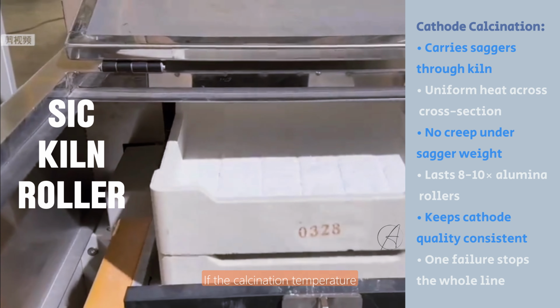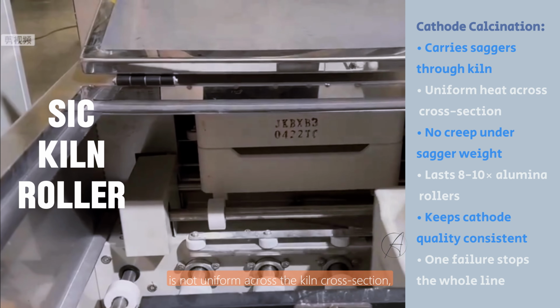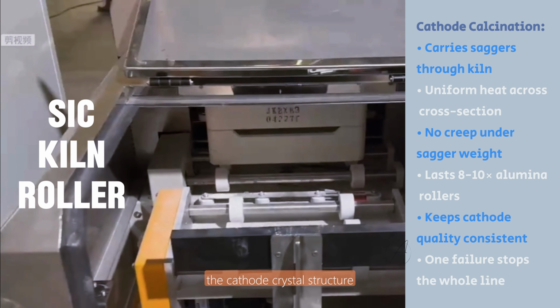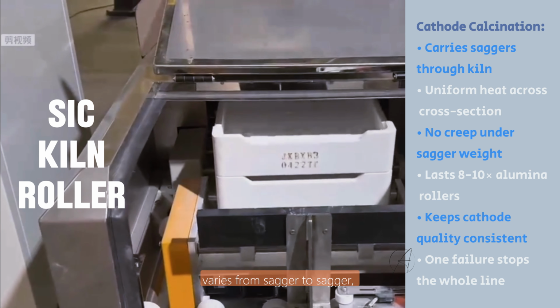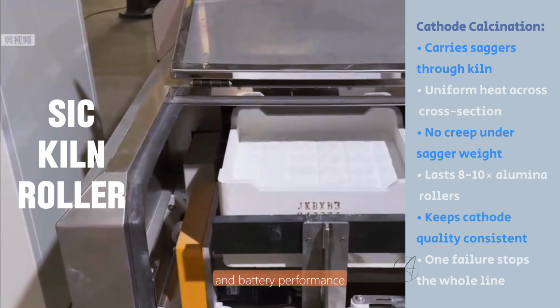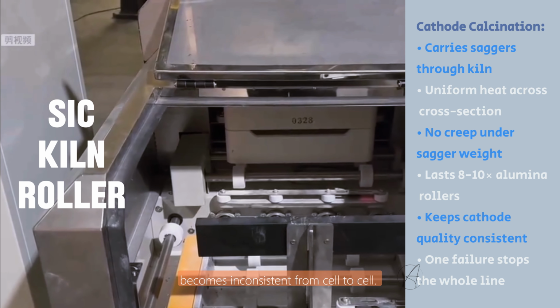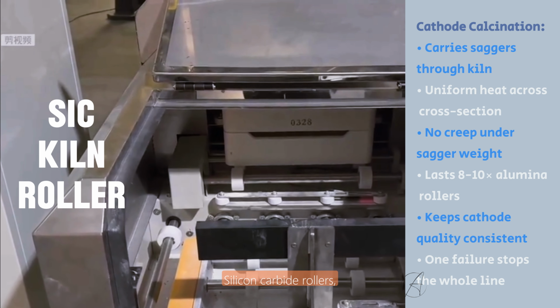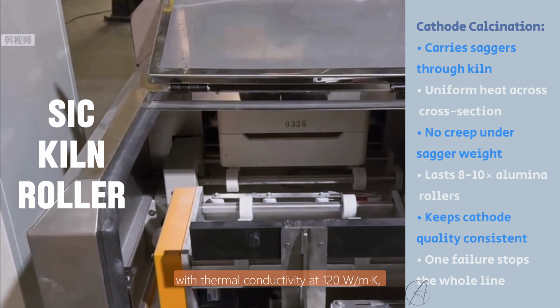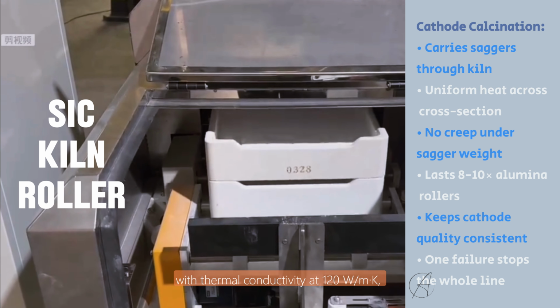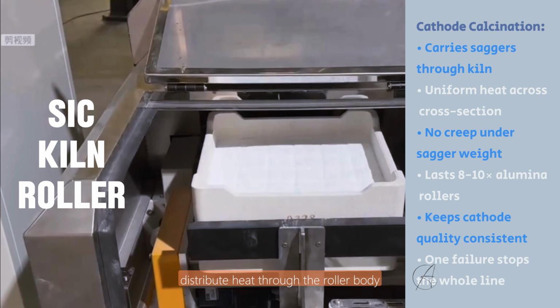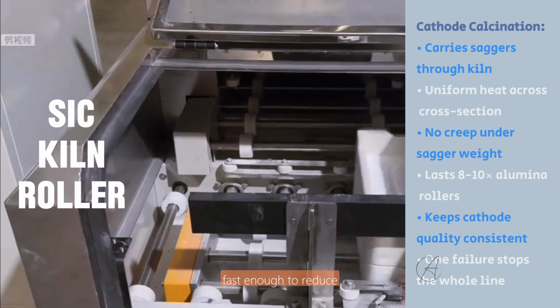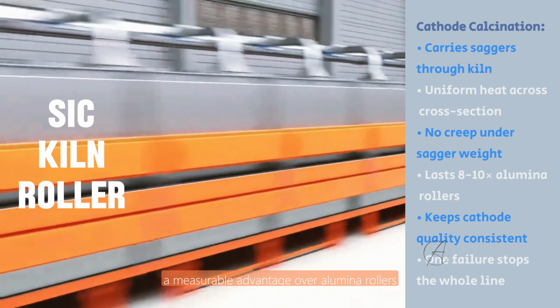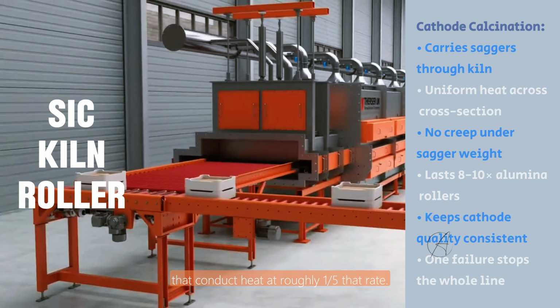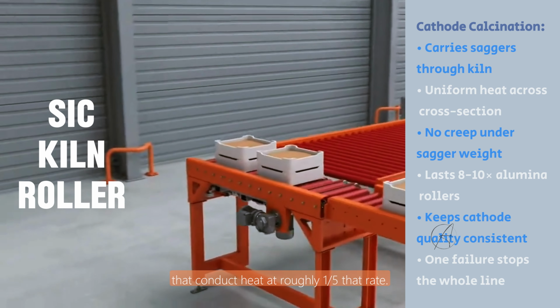If the calcination temperature is not uniform across the kiln cross-section, the cathode crystal structure varies from sagger to sagger, and battery performance becomes inconsistent from cell to cell. Silicon carbide rollers, with thermal conductivity at 120 watts per meter Kelvin, distribute heat through the roller body fast enough to reduce cross-section temperature gradients, a measurable advantage over alumina rollers that conduct heat at roughly one fifth that rate.